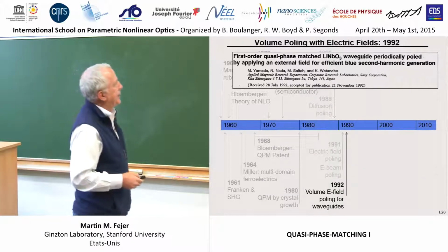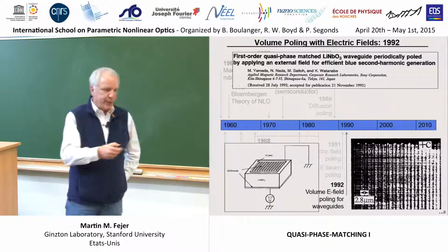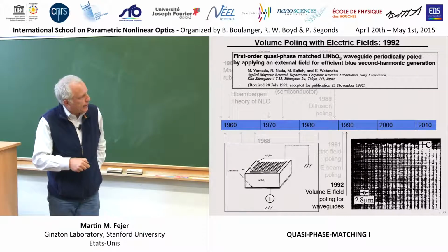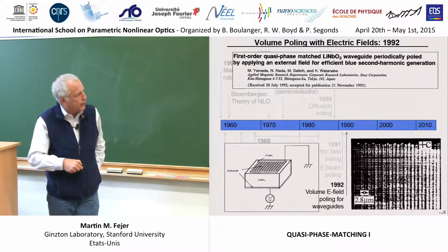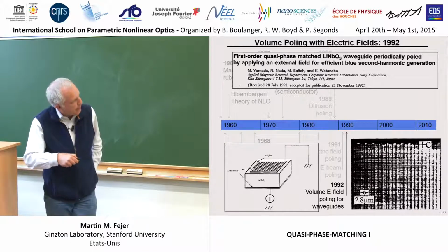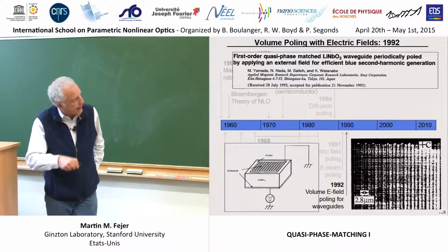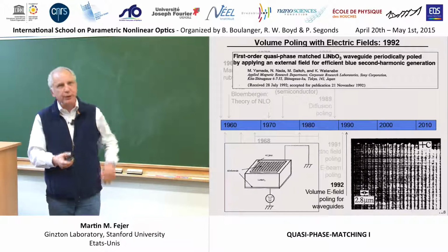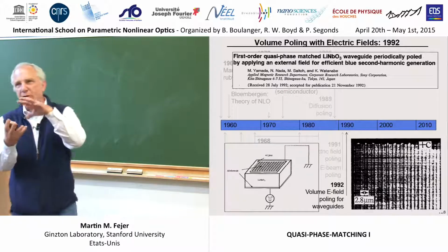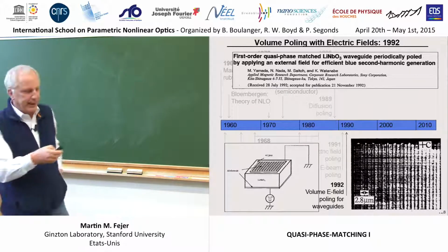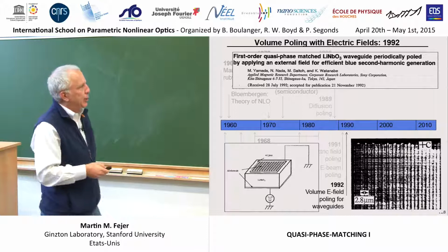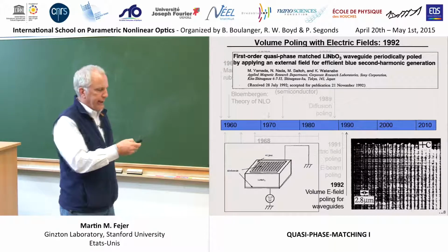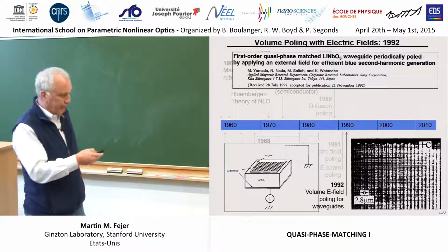And then Sony came up with the next big step, which was to put an electrode structure, a periodic electrode on one face, a uniform electrode on the other face, and apply a pulsed high voltage to this thing, and domains went all the way through this wafer. So that was the first volume poling scheme that actually worked. Didn't work real well. I think this was only done on 100 micron or so thick wafers, but it proved the point.